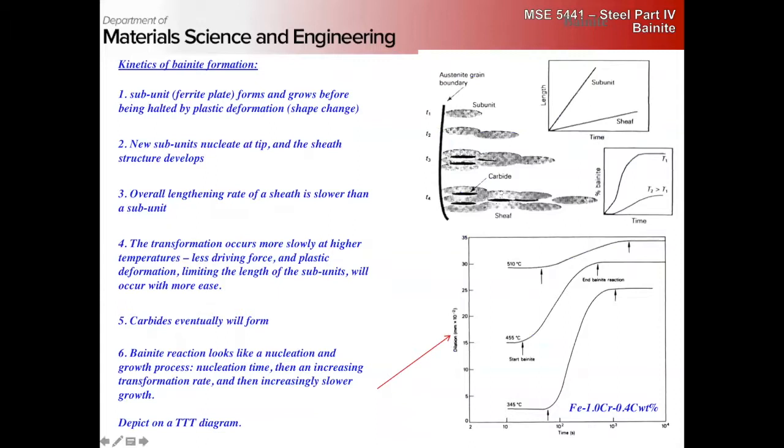if we think about it from the double well potential, and understanding that if you're above the T0 composition, the intersection, your local free energy has to increase by the transformation, it seems to make a lot more sense. Okay, so the kinetics of this, right?